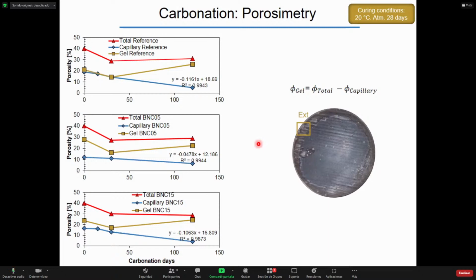And we can see in this graphic of a point near the exposed surface that total porosity decreased over time, as well as capillary porosity. Initially, gel porosity decreases as well, but after 30 days, it starts to increase again. This happens for all three types of mixtures that we used for carbonation. This shows that carbonation modifies the microstructure, reducing larger pores and increasing the smallest ones.